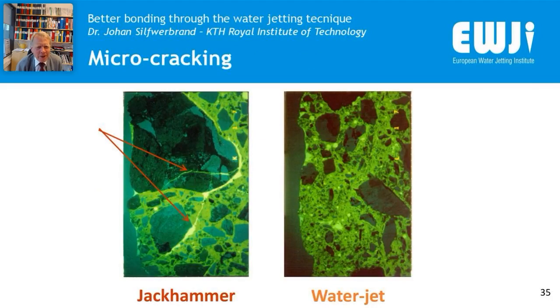Now, one very good thing, as I mentioned already, is that the procedure of removing concrete by using water jet technology doesn't introduce any microcracking. It is perhaps a little bit exaggerated. There will be some microcracking, but they are of minor importance. If you compare it with jackhammers, pneumatic hammers, there is a very large difference. And here is from a thin section analysis. You can see to the left, you have these cracks marked with arrows on a jackhammered surface. And on the right-hand side, you can see a water-jetted surface without any cracks at all.